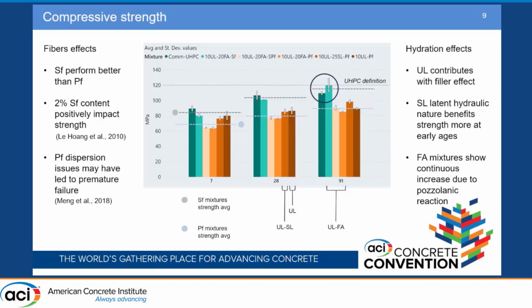One is due to the fibers, where steel fibers perform better than polyethylene ones. This was proven even in the literature, where with up to 2% of steel fibers, you actually benefit strength. While for polyethylene fibers, there are more challenges when you mix them. They form kind of agglomeration, and these agglomerations created weaker spots that led to a premature failure of the specimen.